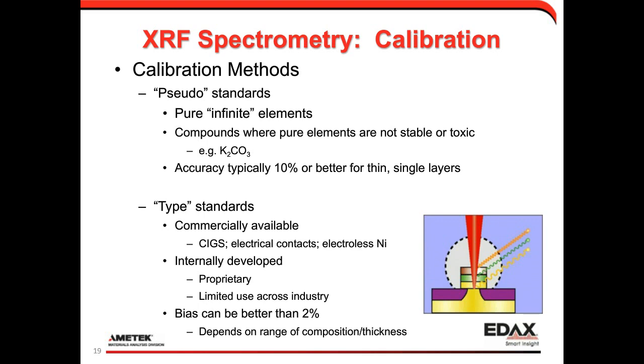Also, if certain compounds are not available as a pure element, for example, something like potassium, you can also calibrate using compounds as well. So we've done things where we've calibrated against potassium carbonate, for example, and we input the compound stoichiometry, and we get out a calibration coefficient for potassium. Now, we're not measuring directly the carbon and the oxygen in that situation. We know the stoichiometry, and so we put that into the model, and that will give us information about if you had so much potassium there and you knew it was in a certain stoichiometry, then you could say, all right, that's how much carbonate is there as well.